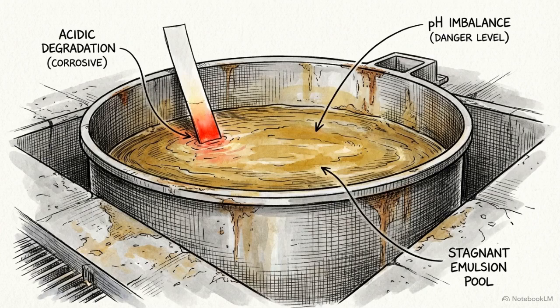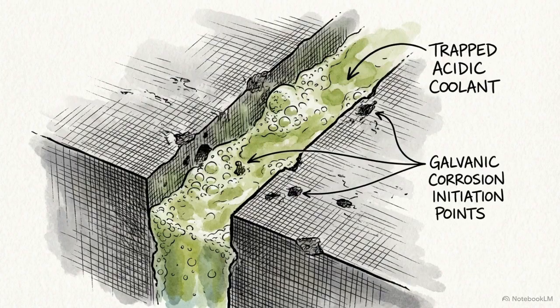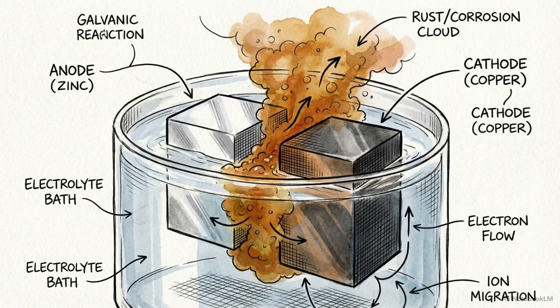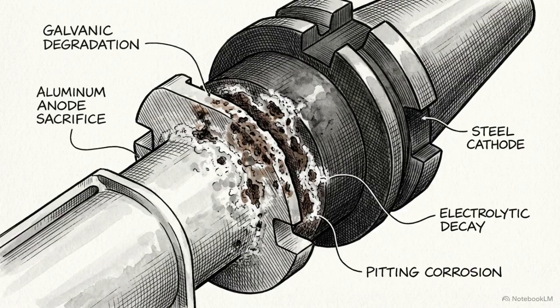Aerospace alloys like 2024 aluminum contain high amounts of copper, making them highly reactive. Water-based coolant emulsions sit in massive open sumps where they lose their pH balance and become acidic over time. When this acidic coolant is trapped, it triggers galvanic corrosion. Galvanic corrosion is an electrochemical process where one metal corrodes when in electrical contact with another, in the presence of an electrolyte, in this case, the degraded coolant between the aluminum and the steel tool holder.